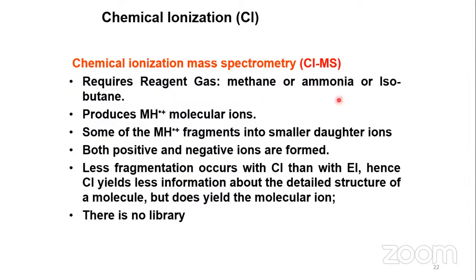In chemical ionization, we use some kind of reagent gas like methane, ammonia, or isobutane, which is admitted first to the ionization chamber. The gas gets ionized, and then in turn, it ionizes your sample to give you MH plus. So you get a protonated ion of the molecule. As MH plus is always there, you get the molecular weight information because you just have to subtract one from the molecular ion weight which you get in chemical ionization, and that would become your molecular weight.